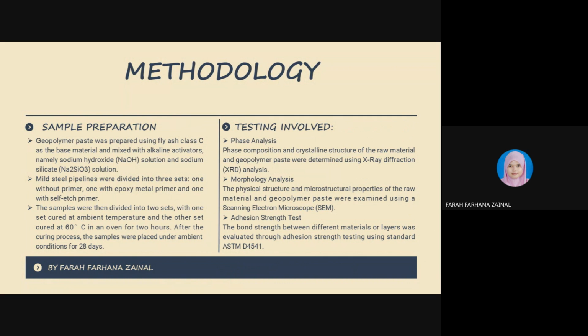So, geopolymer paste was prepared using fly ash class C as a base material and mixed with the alkaline activators, which is the sodium hydroxide solution and sodium silicate solution. And then my steel pipelines were divided into three sets. One is without primer, one with epoxy metal primer, and last one with self-etch primer.